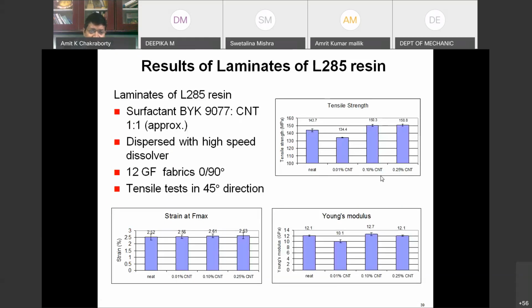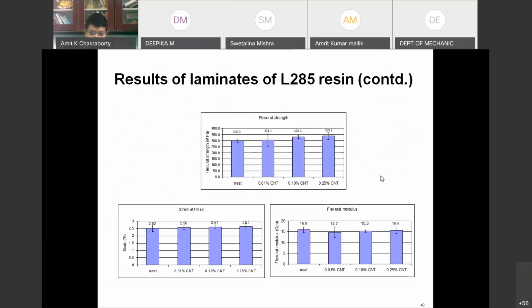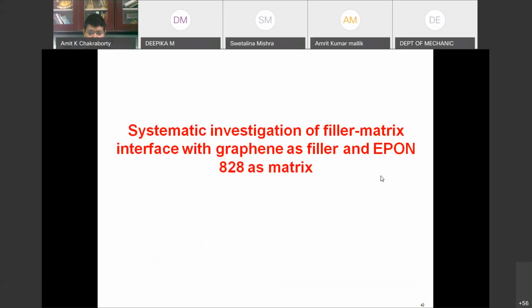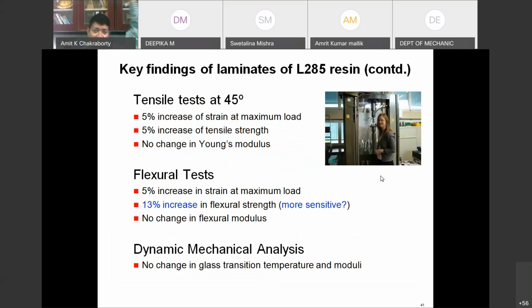I am again skipping these details. I'm going to the conclusion here. So the conclusion slide basically shows that in the laminate we see only a 5% increase in the strain at maximum load, and a 13% increase in the flexural strength. In the tensile strength, we get only a 5% increase, not even 13%, but at least in the bending mode, we get a little extra improvement, but not much.